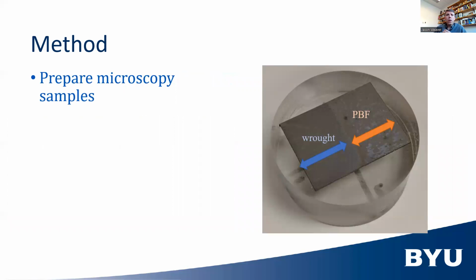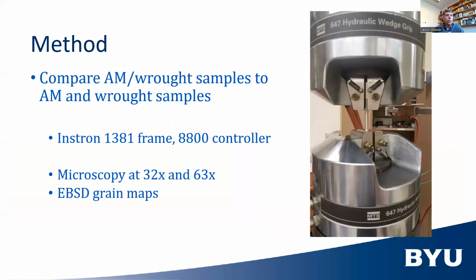We also created samples for microscopy. Again, we had a small rectangular sample that has half of the wrought and half of the powder bed fusion, and then polished them so we could look at it under a microscope and also look at it with electron backscatter diffraction.